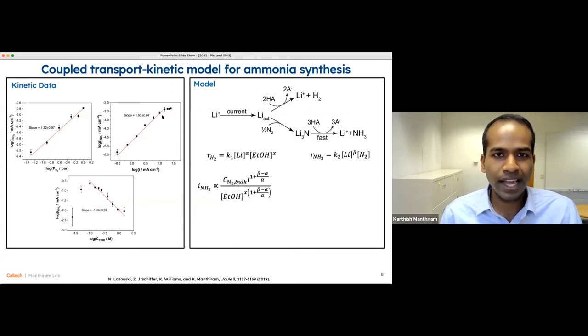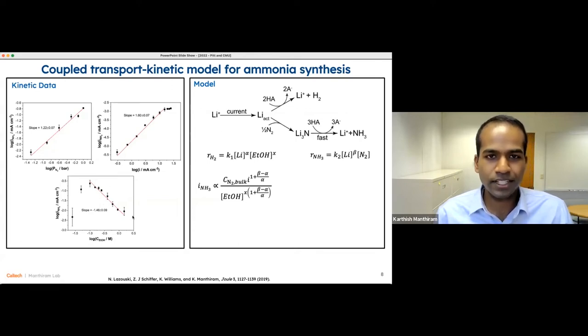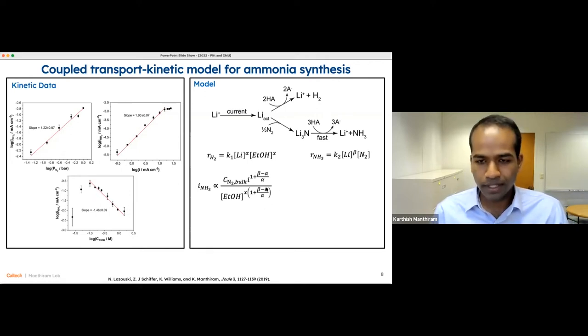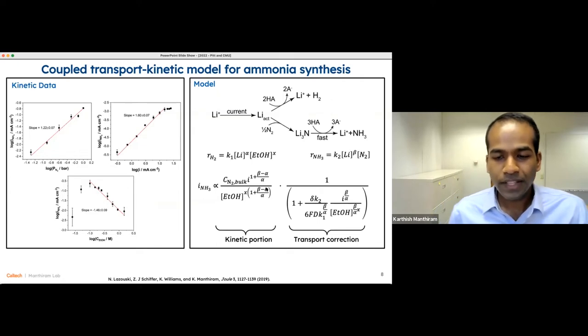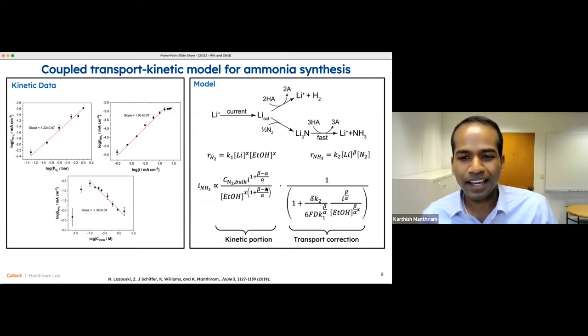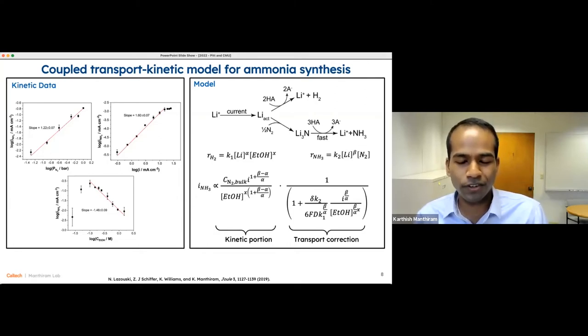So positive 3/2 here and negative 3/2 here. And so this very simple kinetic model is able to capture this equal but opposite order dependence. Now that's just the kinetic portion of the model. And I want to make the argument now that there are, in fact, transport limitations as well, which will really be important for the rest of what I'll share here on ammonia synthesis.